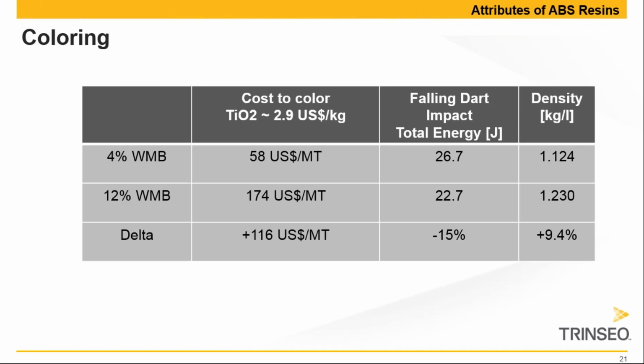Now this will have a direct impact on the cost to make final parts. If I assume here a cost for titanium dioxide of almost $3 a kilogram, then if I move from 4% master batch to 12% master batch to get to the same final color, emulsion versus Magnum ABS, we are looking at over $100 extra cost for coloring for the Emulsion ABS.